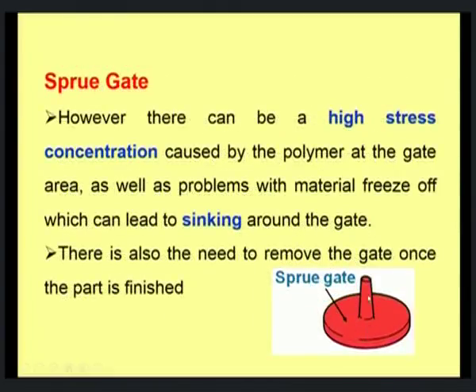The high stress concentration occurs at the surface of this product, and this is caused by the polymer at the gate area, as well as problems with the material freeze off, which can lead to sinking. So, sinking is nothing but the polymer solidifying prematurely before it is converted into the product. This sinking particularly takes place around this gate. There is also a need to remove the gate once the part is finished. Therefore, it requires secondary operations or post processing operations.